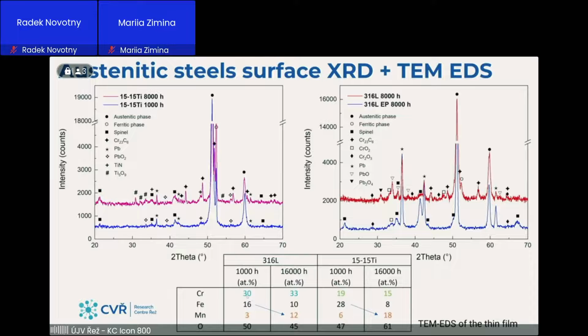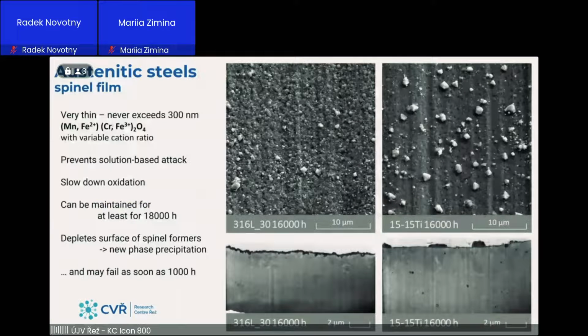Initial higher content of chromium is reflected in 316 by higher content of chromium in the spinel phase. In 1515 titanium, it is only 15% of chromium, so there is at the beginning 19% of chromium in the spinel and then it decreases, and iron is replaced by manganese. Quite interesting. This is the structure, the phase we identify there. It can be there even after 20,000 hours. So it prevents solution-based attack, slows down oxidation, and may of course fail as soon as 1,000 hours.